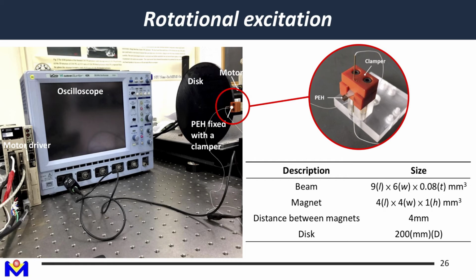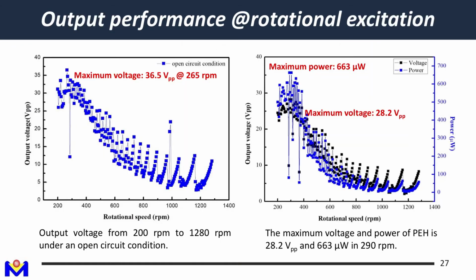So we replace the proof mass with a magnet. And for the rotational disc, if we also have magnets along the circular direction, then we can create mechanical, magnetic plucking. And with this kind of rotational excitation, because of the harmonics of the rotational speeds, you can expect a broader operating range. At different rotational speeds, you can get quite good output. And the overall voltage output and power output are also quite good compared to base excitation.